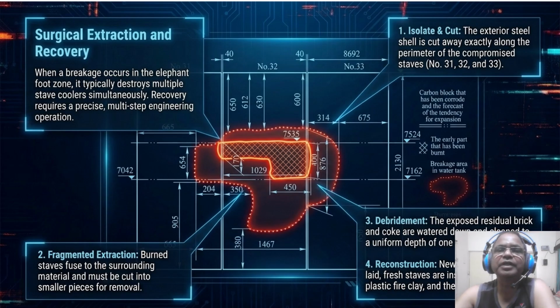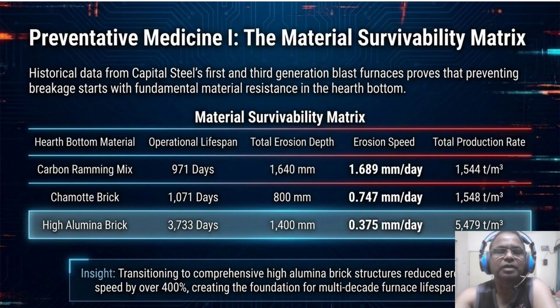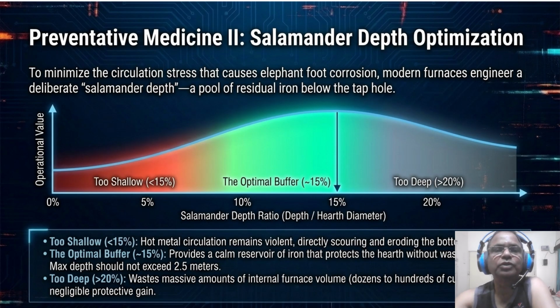So coming to our preventive medicine 2, which is about salamander depth optimization to minimize the circulation stress that causes elephant foot. Consider engineering a deliberate salamander depth, a pool of residual iron below the tap hole. So if the depth ratio is too shallow, less than 15%, the circulation remains violent, directly hitting the bottom lining. If it is too deep, over 20%, you are wasting hundreds of cubic meters of internal volume for negligible gain. So the sweet spot is that 15% optimal buffer.